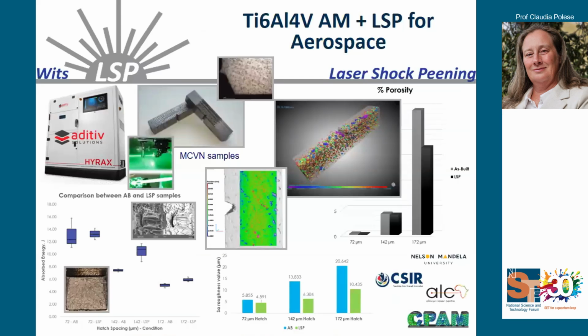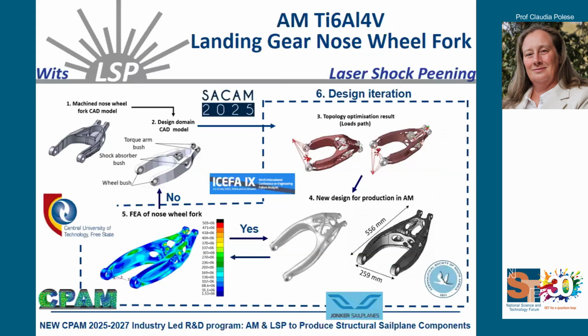Colleagues from aerospace were very interested in this. So currently we're working again on titanium. We just acquired a new additive manufacturing machine, so it's coming to the lab very soon. And we saw that applying laser shock peening, we again have very, very good results with the porosity. So this is obviously a big achievement, especially for aeronautical application. But we also try to see how we can develop technology, so, for example, a new inspection method, a new testing method that can simplify the adoption and the uptake of additive manufacturing and laser shock peening within the aeronautical industry.